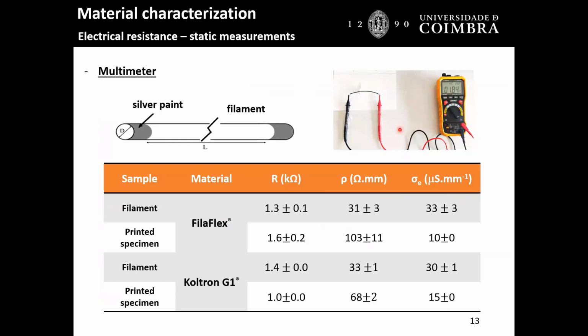First of all, we tried with a simple multimeter, and we made a painting with silver just to enable the contact more easily, okay? And we measured the resistance, and calculated the resistivity and the conductivity. What we saw with this technique is that we always have less conductivity in the printed specimen than in the filaments, okay? I didn't tell you, but the printed specimens have a 100% infill of plus 45, minus 45, which means that the filaments and the reinforcement may not be aligned in the direction of the testing procedure, and that may be the reason for this lower conductivity of the printed specimens.